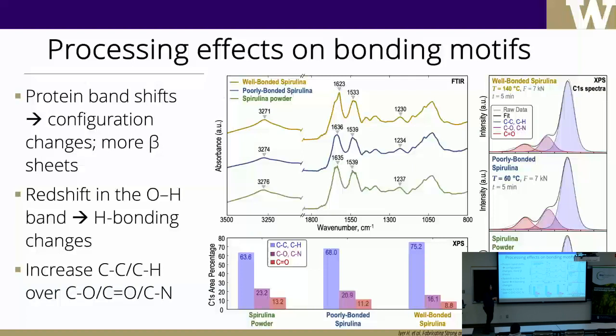And then we have, of course, another red shift in the OH bond. So we know that there are also changes happening in our hydrogen bonding network. We're not measuring hydrogen bonding from FTIR, just seeing that there is a small shift between the powder and the well-pressed material. Then we go in with XPS, and we do the convolution for the carbon and the oxygen peaks. And here we have the ratios between carbon-carbon, carbon-hydrogen, carbon-oxygen, carbon-nitrogen, and carbonyl bonds. And we see that between the powder and the poorly or the well-bonded material, basically our ratios change.